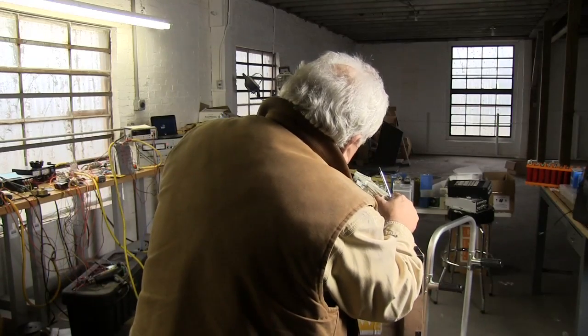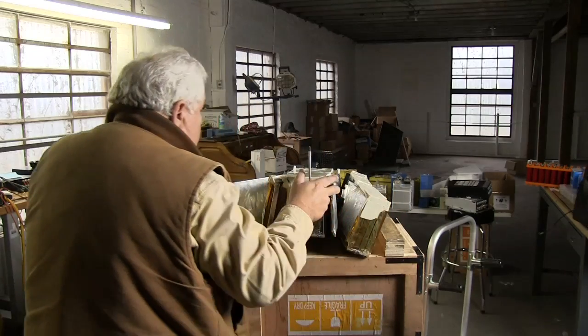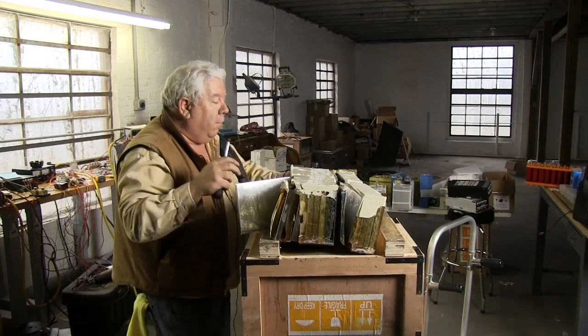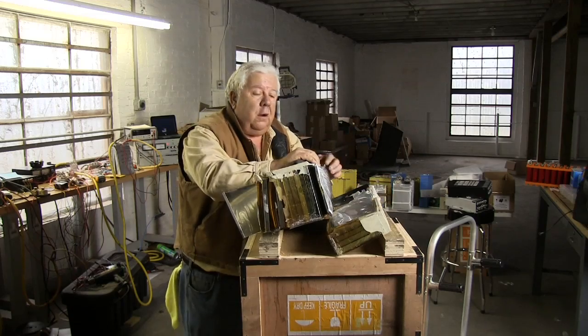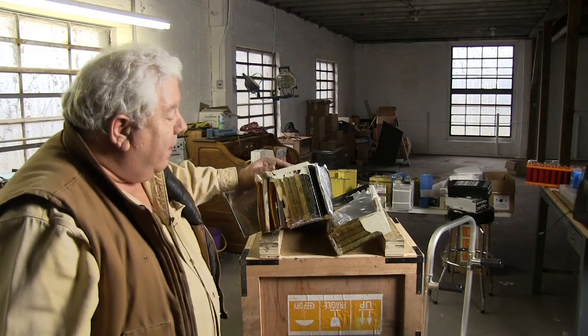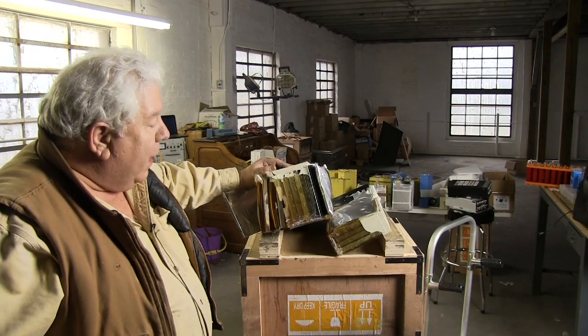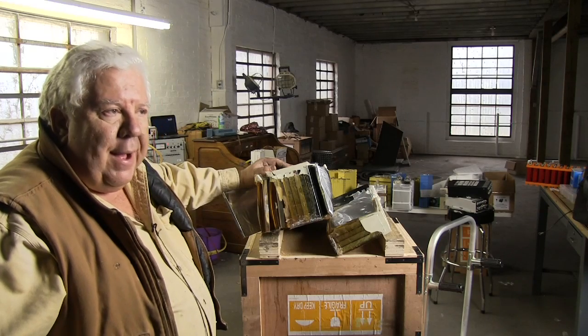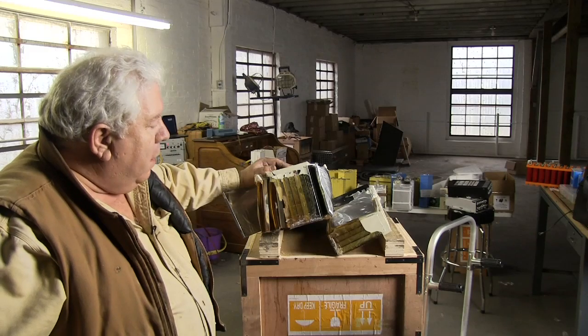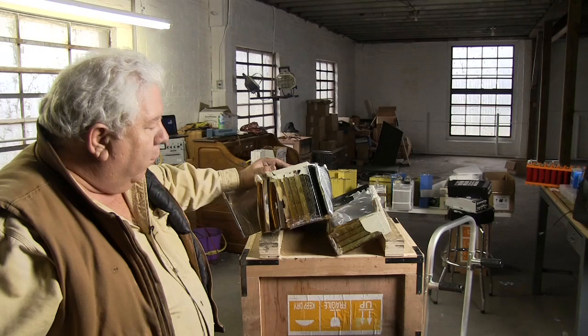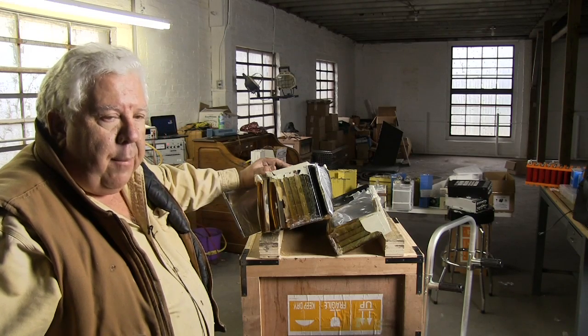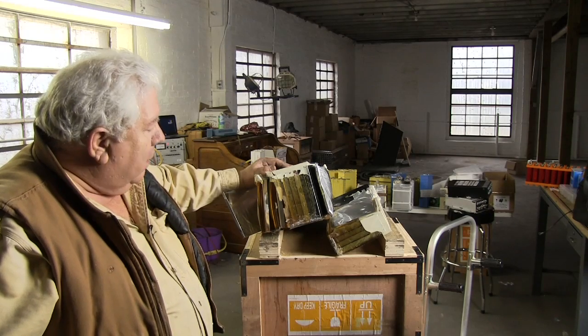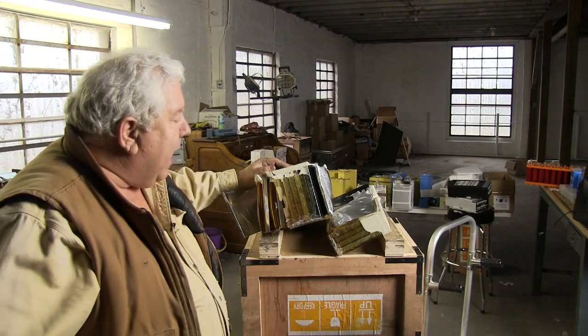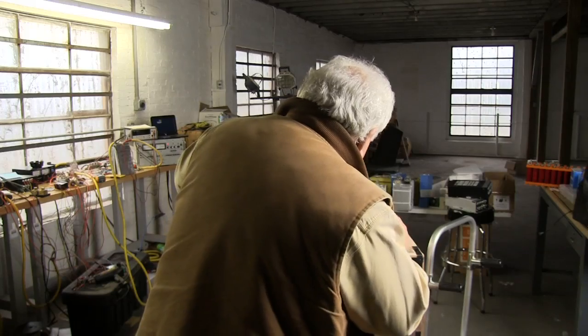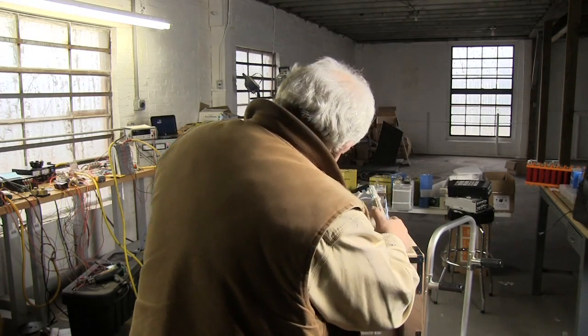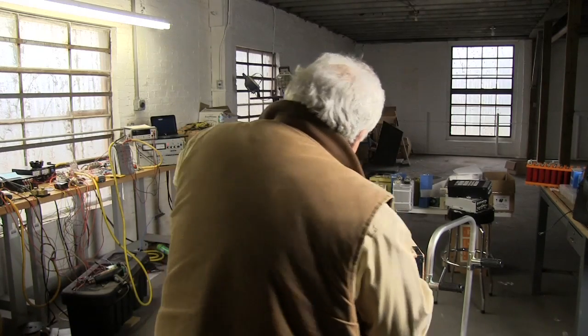Really did bust lengthwise and really made a mess. And this was 48 cells, probably $1,400 worth of materials. What happened was I had 75.75 amp hours on it. I cast it in resin, drained it, and somehow got about 65 amp hours out of it, and it was quite low, down around 2 volts per cell, 24 volts. So then I charged it back up about 65 amp hours, and it blew up. And so clearly the capacity of some of these cells was diminished. And I'm not sure why that was so.